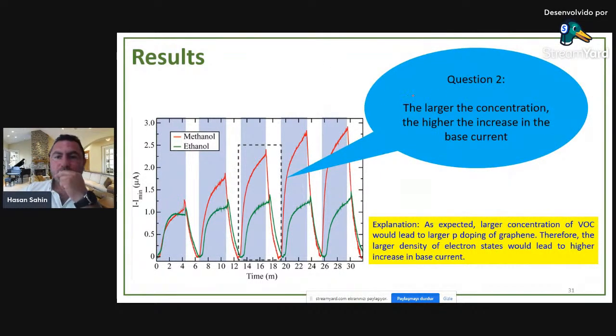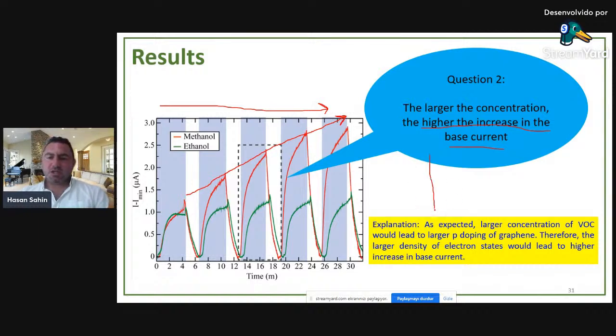And question 2: it seems that in time, if you increase the concentration of a volatile organic compound, methanol or ethanol, the larger the concentration, the higher the increase in the base current. You see, in time, if you increase the concentration, base current becomes larger and larger. The explanation is easy, as you expect. A larger concentration of VOC would lead to a larger amount of p-type doping, so it will be increasing the base current more and more. Therefore, the larger density of electron states would lead to a higher increase in the base current.